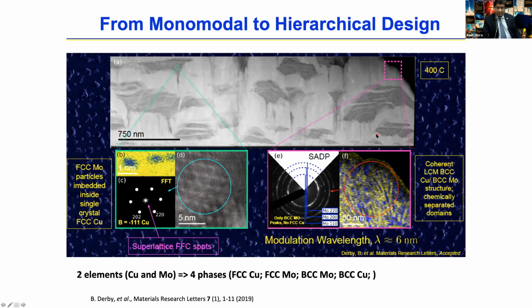If you blow it up, it actually has striations of this maize and blue striations of copper and moly-rich regions, where you have this lateral concentration modulation morphology, but copper is body-centered cubic. So in this case, copper takes on a metastable structure. It is body-centered cubic, lattice matched with the matrix body-centered cubic moly, and creating these kinds of phase-separated domains that make up the matrix.